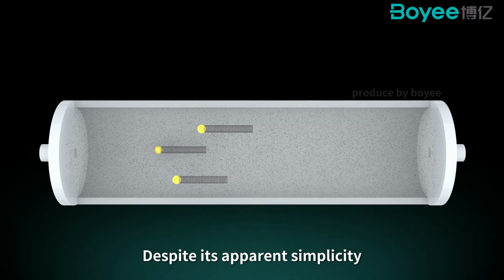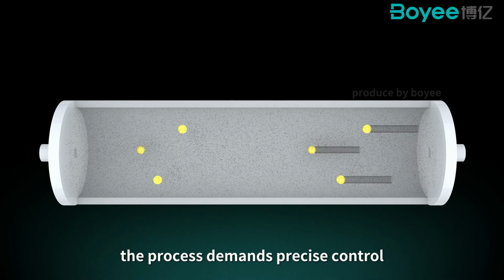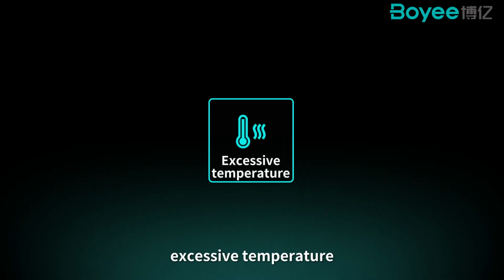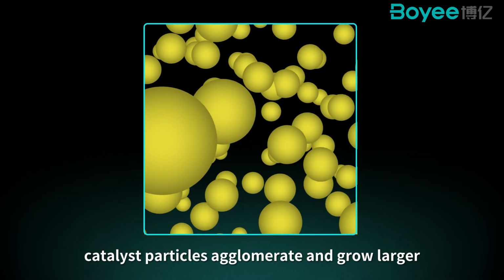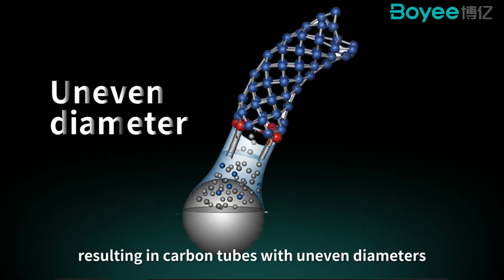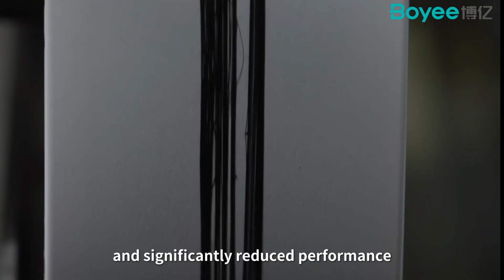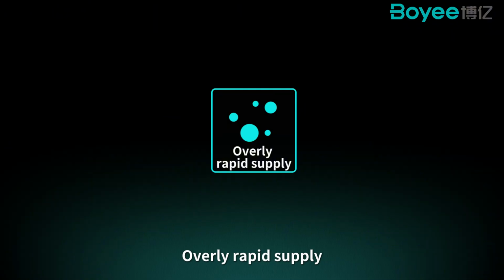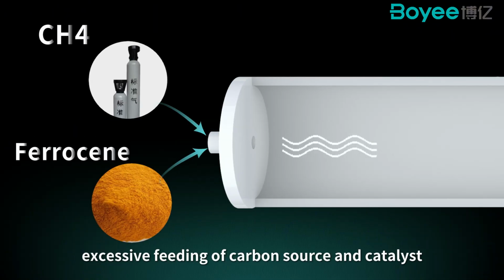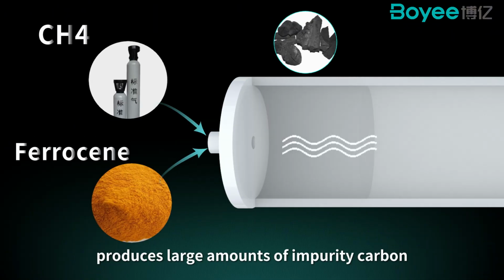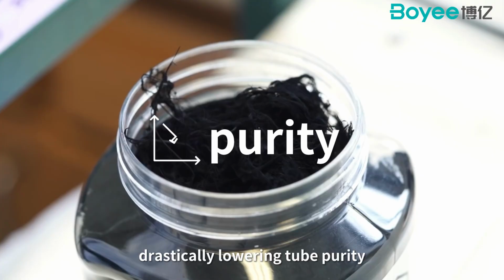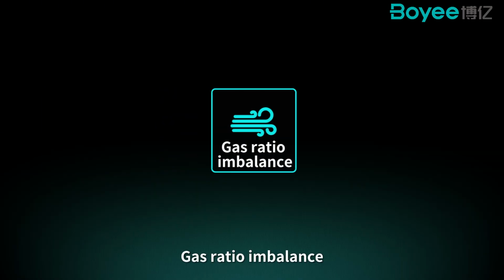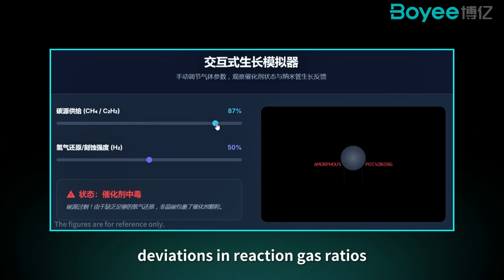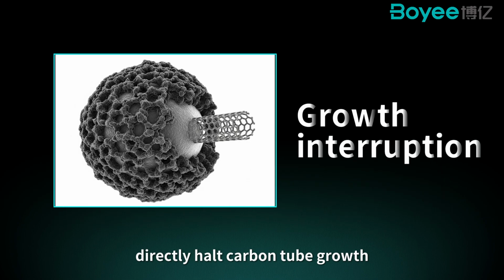Despite its apparent simplicity, the process demands precise control. Excessive temperature: catalyst particles agglomerate and grow larger, resulting in carbon tubes with uneven diameters and significantly reduced performance. Overly rapid supply: excessive feeding of carbon source and catalyst produces large amounts of impurity carbon, drastically lowering tube purity. Gas ratio imbalance: deviations in reaction gas ratios directly halt carbon tube growth.